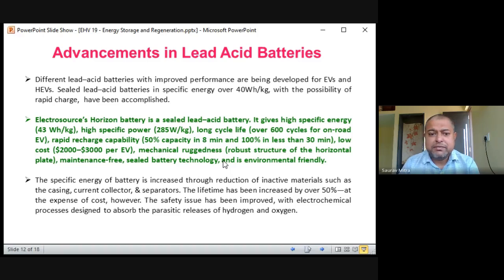Rapid recharge capability: 50% capacity in 8 minutes and 100% in less than 30 minutes. So within 30 minutes, it can get charged up to 100%. Low cost: $2,000 to $3,000 seems to be a low cost. Mechanical ruggedness: robust structure of the horizontal plate, maintenance free, sealed battery technology, and environmentally friendly. All these things are positives of lead acid battery. Specific energy of the battery is increased through reduction of inactive materials such as the casing, current collector, and separator.